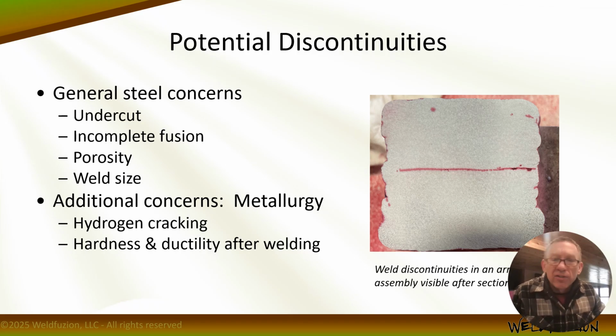Their carbon content is really at the high end of low carbon or at the low end of medium carbon steel, so it's not all that great of a concern. But because of the alloying, the carbon equivalent is much higher than that, and they're going to behave like a high carbon steel. So we need to really worry about hydrogen cracking and managing the balance between strength and ductility after we're done welding, or we could actually screw up the heat treatment and soften the material, or we could cool it too fast, make it too brittle, and it's not going to fail in the manner that it was intended.